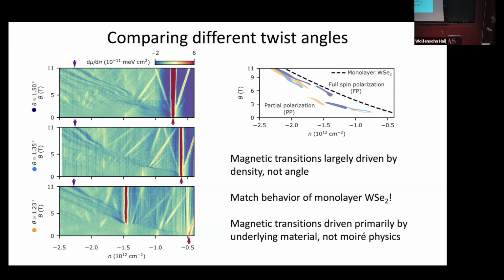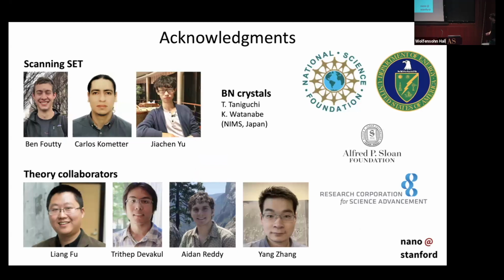That means that although the magnetic transitions have a really dramatic impact on what sorts of ground states you realize in the Moiré system, on the other hand, where they occur seems to be primarily dictated by the underlying material. And so this is a hint, I think, that if you want to try and figure out where in different portions of phase space to look for different interesting states, which may require magnetic polarization or may actually require not being polarized, then it may be helpful to look at the underlying material properties themselves to figure out what's the most promising place to look. So with that, I think I'm mostly done.